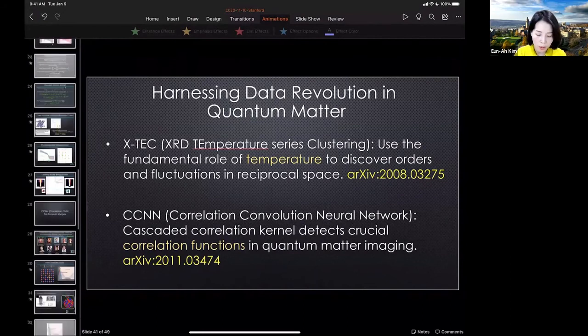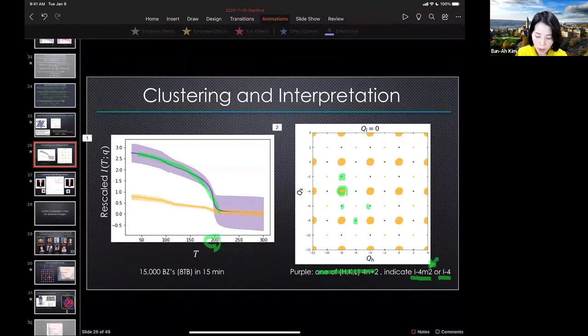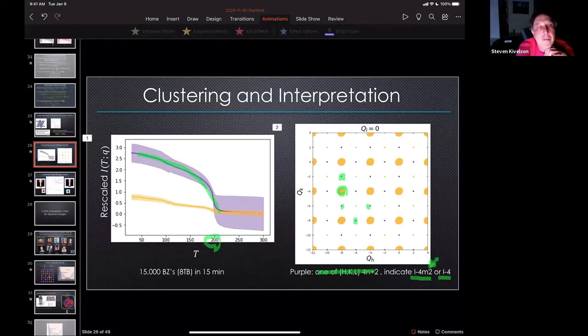Right. We knew it was point group symmetry breaking, but because the symmetry of the high temperature phase was really large, it was a cubic system, there were many different ways. There's a whole branching of what could be the lower temperature phase. And because there is no new superlattice peak showing up, it becomes sort of a crystallographic question. But the distortions that give rise to the symmetry breaking are very small. So it was hard to detect exactly what was going on.